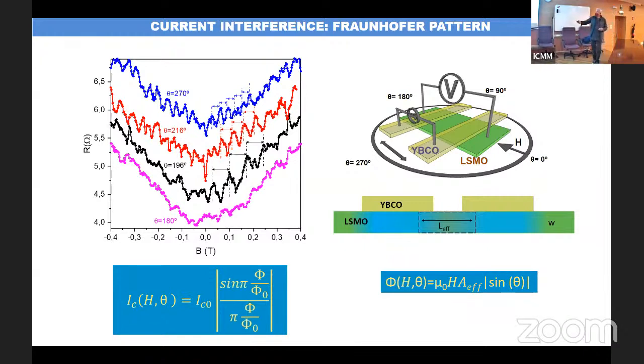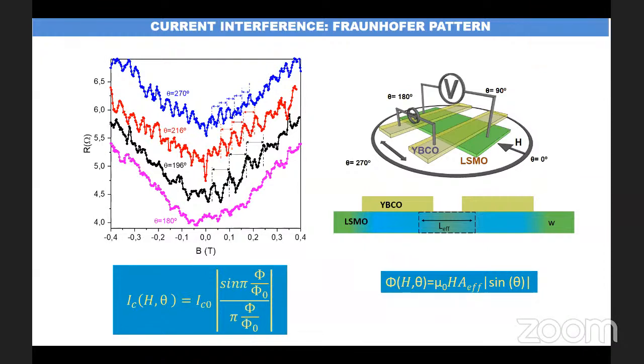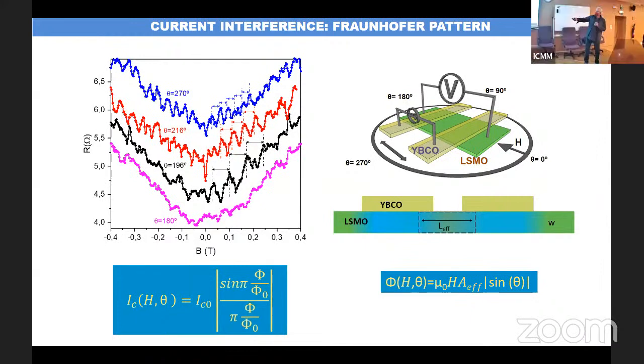Now, this is resistance as a function of magnetic field. And you may see that at this level, the modulation of resistance in the Fraunhofer oscillation is below one ohm, but you can measure it, no problem. So we are above the critical current, but we feel the critical current. Now, let me think of your question, whether this measurement would or would not feel a zero pi transition if it would happen.